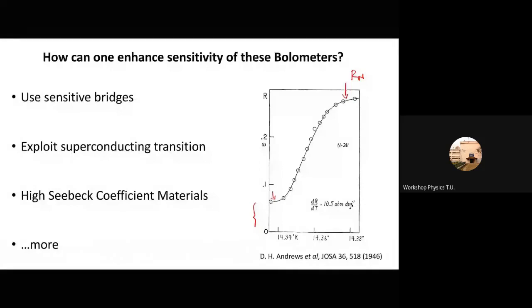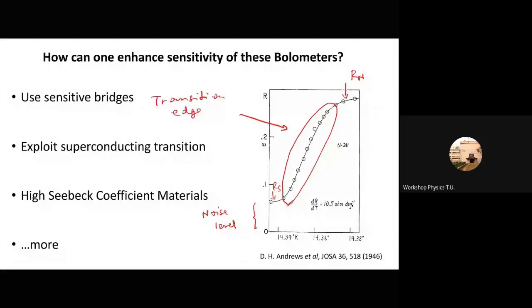Here there is a large change in resistance from the normal state to the superconducting state, and this is the noise level in their experiment. What they suggested was, because there is a sharp change in resistance in this range, one can implement it as something called a transition edge detector based bolometer.